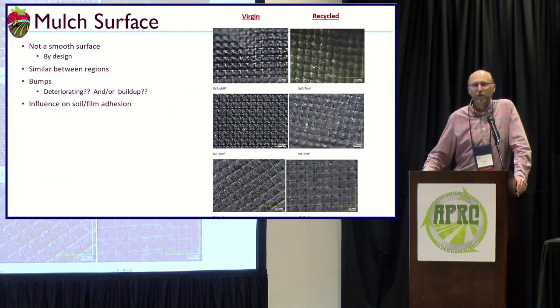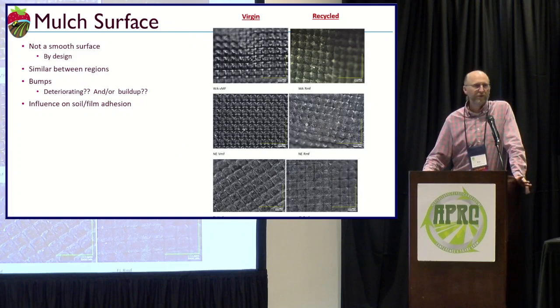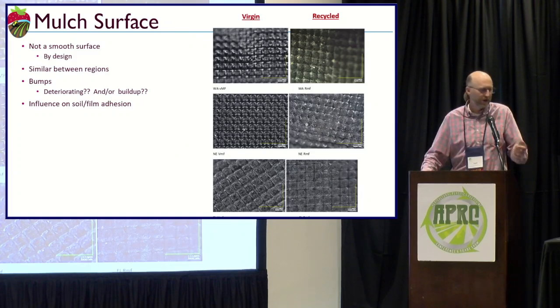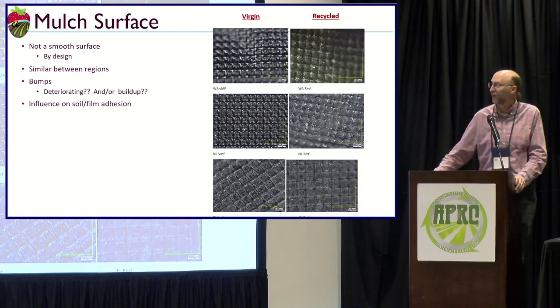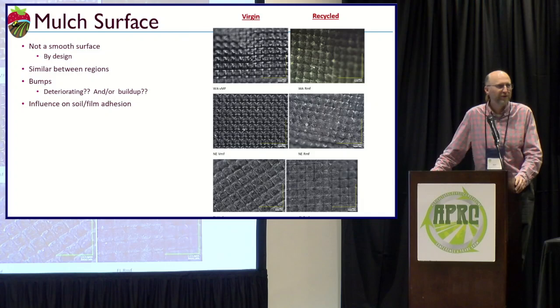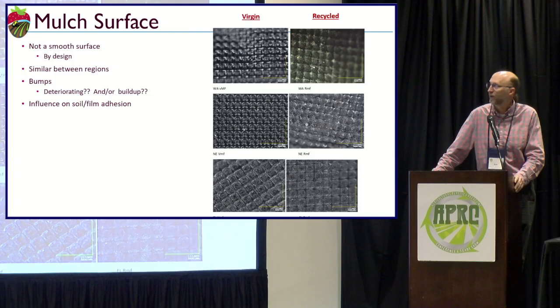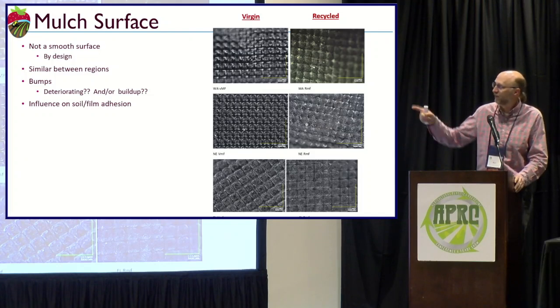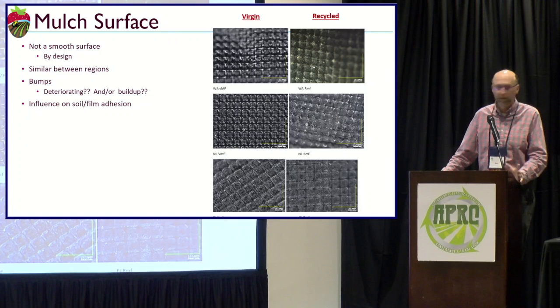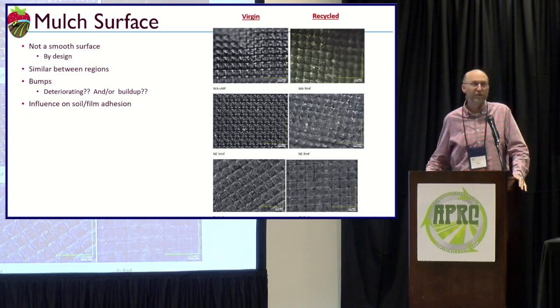The other thing that we looked at is what these things look like on the surface. If you look at a mulch film right now, it looks pretty nice and smooth. But when you actually do a microscopic evaluation of it, it's not very smooth. It actually has a micro embossing technique that they use. The good thing is that between the different sites we have, Washington, Nebraska, and Florida, they're all pretty much the same, and so we're happy with that.